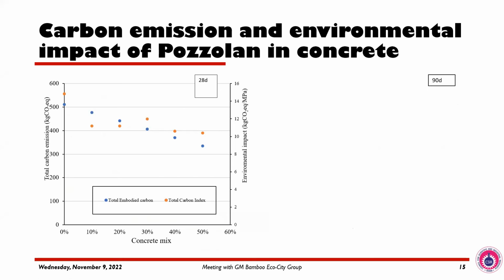Okay, so let's continue. After doing this efficiency factor, I also did some work on carbon emission and environmental impact. This is also very key. In this area of cement science and concrete, you have to be mindful of these two things. Environmental impact is a ratio between the total carbon of your material you are generating against the strength you are achieving at the required time. And in the standard, the required time is 28 days. But when you are using pozzolans, because pozzolan has a late setting time, we actually require to go above the 28 days.